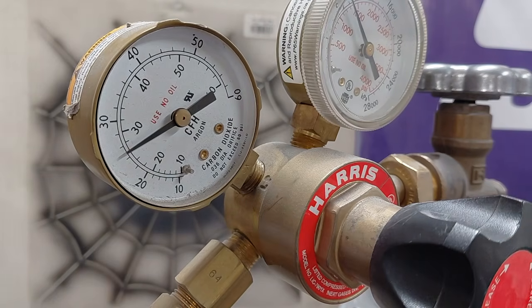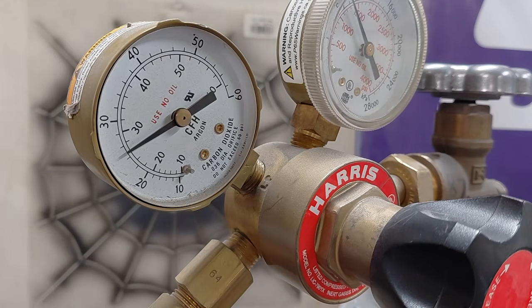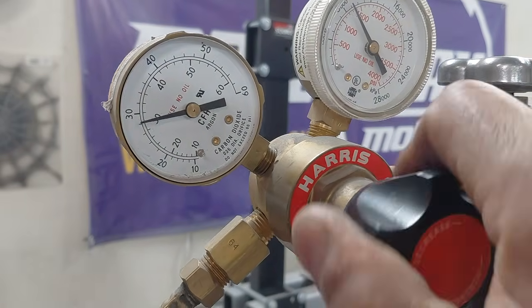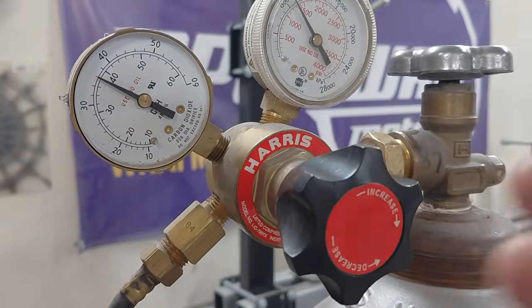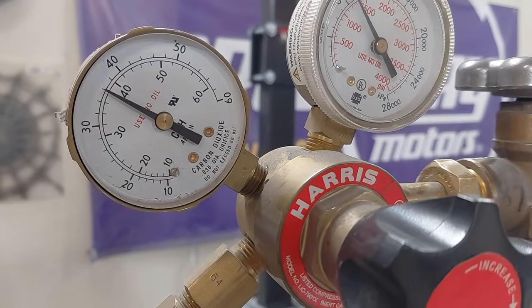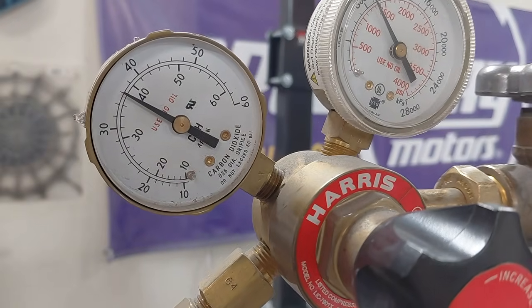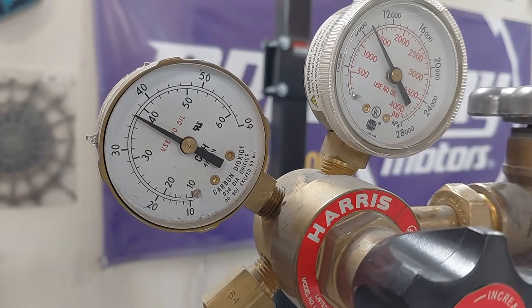If you have too little shielding gas, you will have issues with porosity. I would rather waste just a little bit of gas, not have an issue with porosity, and not have to come back and grind a weld out and redo it. But if you set the flow rate too high, you can actually pull oxygen into the weld puddle or weld pool, and that will give you porosity also.